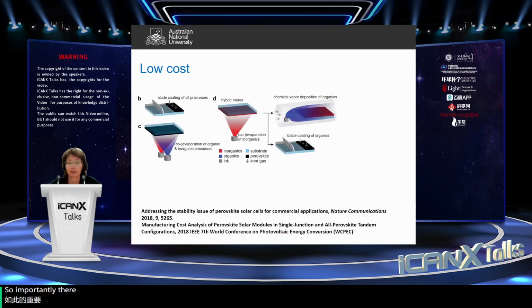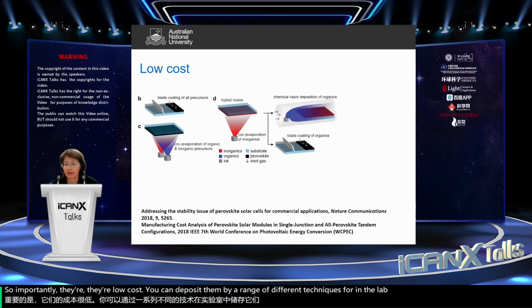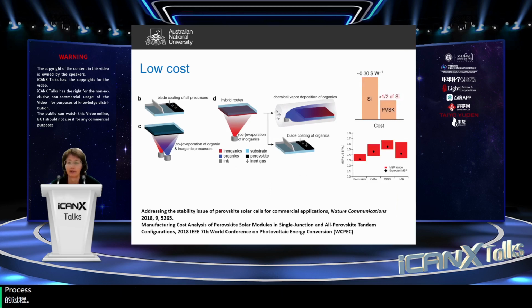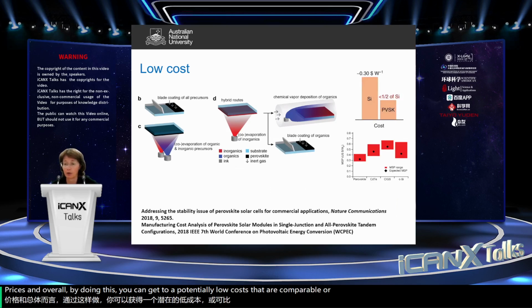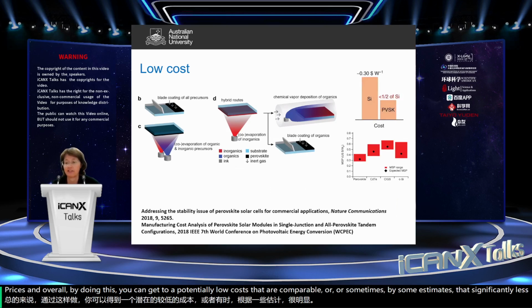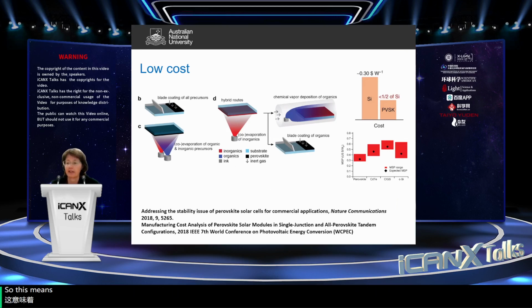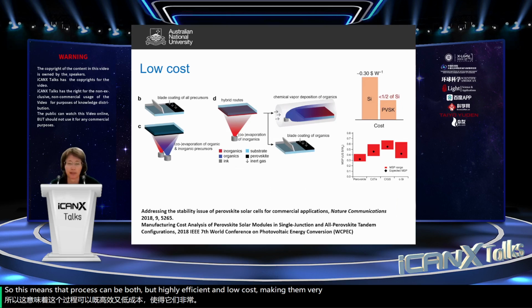So importantly, they're low cost. You can deposit them by a range of different techniques. In the lab, we usually use spin coating, but it's also possible to use blade coating, or co-evaporation of the precursors. You can use co-evaporation together with chemical vapor deposition, or together with blade coating in a two-step type process. Overall, you can get to potentially low costs that are comparable, or by some estimates significantly less than silicon. So this means that perovskites can be both highly efficient and low cost, making them very prospective for tandems.